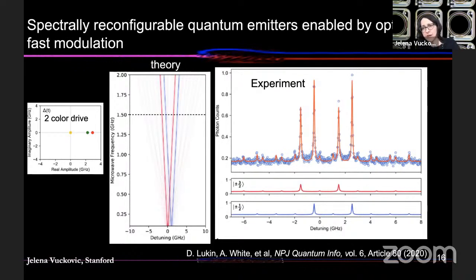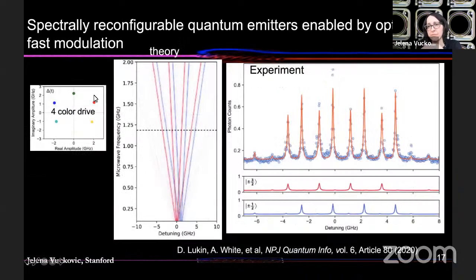When you change the drive to a 4-color drive, I mean 4 harmonics in your microwave drive, then in your output spectrum, you will see 8 peaks. And again, normally you would see only 2 peaks, but here you see 8 peaks because you have 4 peaks that emerge from the spin 3/2 manifold and 4 peaks that emerge from the spin 1/2 manifold. And you can change the symmetry by playing with how much contribution you have in different harmonics. You can change the symmetry of the spectrum at the output and make it look very different from this one.